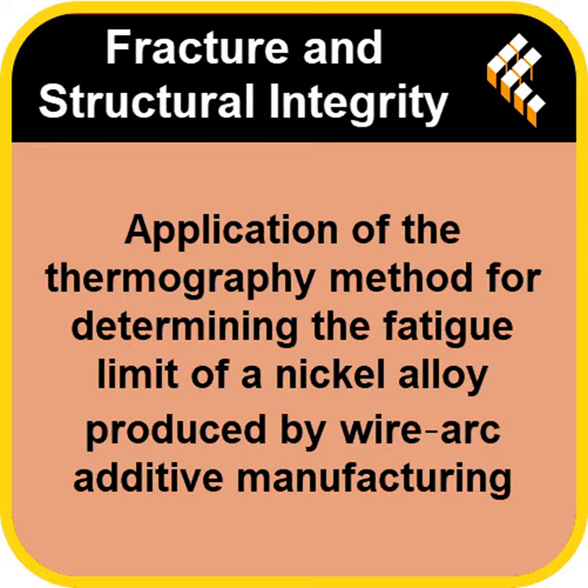It creates this really clear picture, a graph with two very different slopes. Below the true fatigue limit, the plot is almost flat, a really shallow slope. The material's fine, it's not dissipating much energy, but the instant you cross that fatigue limit, the slope of the line becomes dramatically steeper. Damage has started, and that internal energy dissipation just skyrockets. So the fatigue limit is the exact point where those two lines intersect. Yeah. Where the slope abruptly changes.